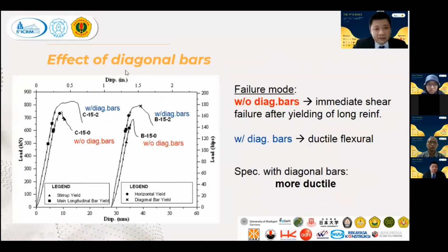Secondly, let's see the effect of diagonal bars. We can see that whether they are column stub or bearing plate, with the addition of diagonal bars, it shifted the load deflection curve from the ductile shear behavior into a ductile flexure behavior. Although we observe some yielding of the reinforcement for the specimen without diagonal bar, this does not last long.